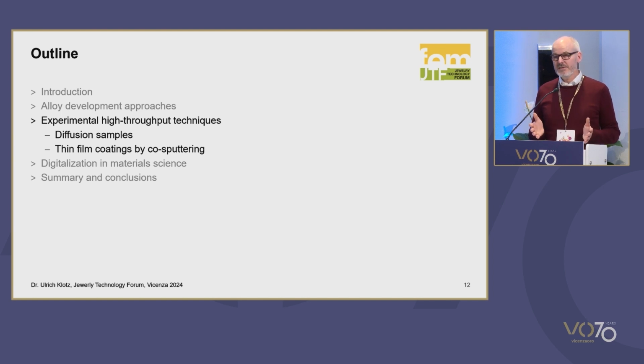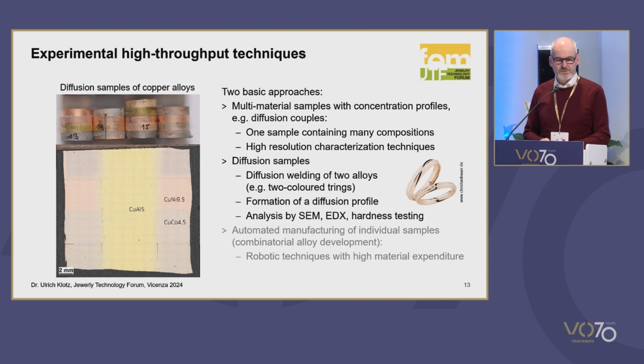But screening techniques are based on samples that show inside the sample there's a certain composition range. And within one sample, we can characterize many alloys without making 20, 50, hundreds of samples. And there are two techniques that I would like to show that are used. One is so-called diffusion couples.